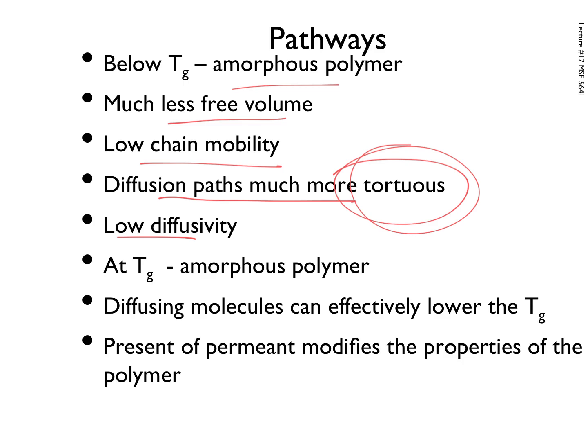But where things get interesting, and this relates back to this self-catalysis effect, if we have an amorphous polymer and we are at the glass transition, these diffusing molecules can do what we now know they can do. They can increase the amount of free volume present in the system, and that can effectively lower the glass transition. So we have a situation in which what's diffusing causes it to go through the glass transition and triggers enhanced diffusion. And this is one of the primary reasons why Fick's law no longer applies, because this kind of stuff can happen. Question?